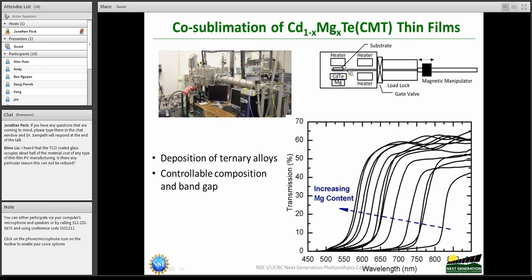Now, this ternary alloy scheme is not just restricted to magnesium alone. There are potential possibilities with selenium, zinc, and there is some advantage to running under excess cadmium or excess tellurium. And this whole thing has been added with metallo-organic injection so that we can add other elements and also dope the material. And so potentially the amount of different materials we can look at here is quite enormous, and that's what we will be needing to make the advanced single junction and the triple junction.